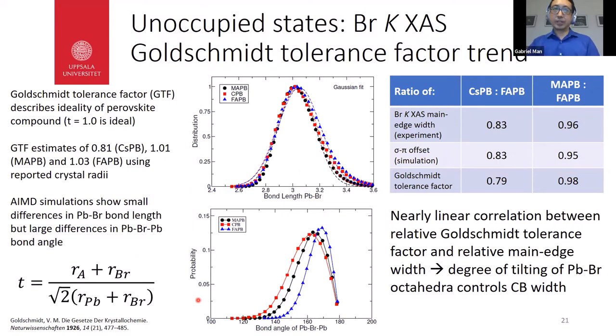To understand the origin of this trend, I've looked more at the crystal structure. The Goldschmidt tolerance factor, shown as this equation in the lower left, is a structural-only descriptor that's very old, but still widely used. The ideality factor of the perovskite is nominally one. Using standard values for the crystal radii, from Shannon's crystal radii and from some computed values for the average radius of methylammonium and formamidinium, we get these Goldschmidt tolerance factors. If we again take ratios of these factors, we get something that lines up pretty well between the relative Goldschmidt tolerance factor, the sigma-pi offset, and also the bromine K XAS main edge width. That's a nearly linear correlation between a structural descriptor and a main edge width.